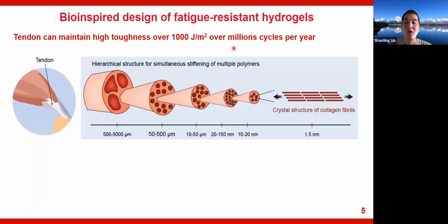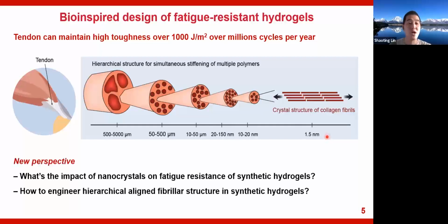Such remarkable fatigue-resistant properties are really attributed to 2 physical reasons. The first one is the hierarchical structure of aligned fibers across length scales, which enables simultaneous stiffening of multiple polymers. Beyond that, the presence of ordered collagen fibrils is also known to be a key factor. So naturally, we are curious about two perspectives. The first is what the impact of nanocrystals is on fatigue resistance of synthetic hydrogels. And the second is how to engineer such a hierarchical aligned fibrous structure in synthetic hydrogels.